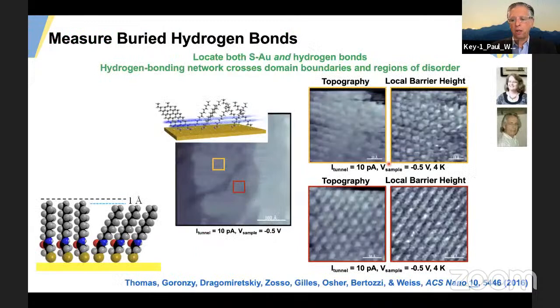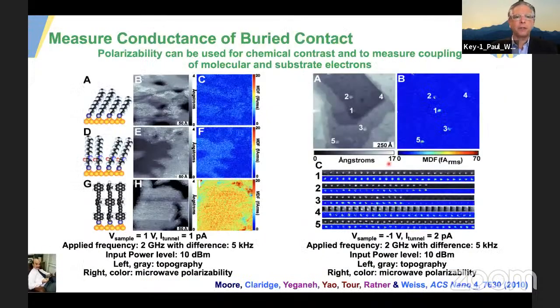We're also interested in the contact conductance. And so we use a polarizability measurement where the contribution to the molecular polarizability includes the electrons from the substrate if the contact is sufficiently conductive. So we could look at the same molecular switches, individual molecules, in the on versus the off state and show that the polarizability changed by a factor of 2. And that gave us a measurement of what the conductance of the contact was. And so even in the non-trivial cases, we have a way to measure buried contacts using these tools we developed along the way.